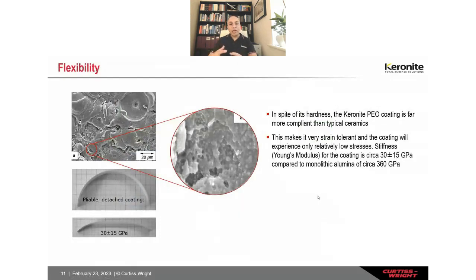Flexibility is another interesting characteristic of the PEO technology. Because of those plasma discharge events, millions of them happening on the surface, you have these microscopic pores, shrinkage cracks, etc. That allows you to make the coating very flexible. One of the Cambridge University PhD students measured the Young's modulus of these coatings and found it to be an order of magnitude less than monolithic ceramic. That allows the coatings to flex and makes them very strain tolerant.